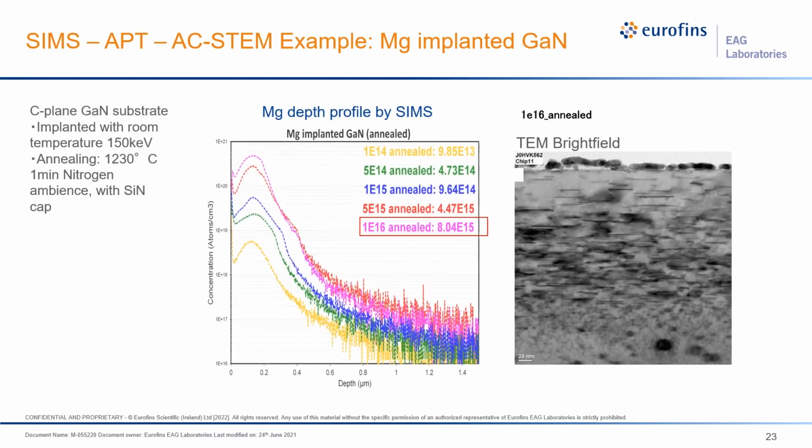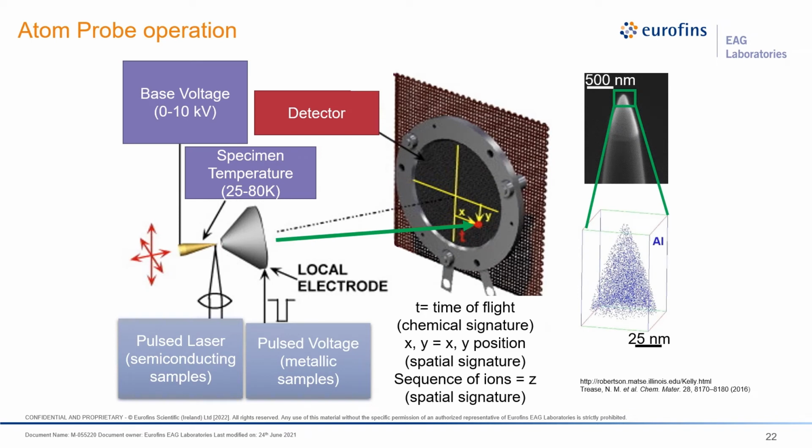This is very useful in the sense that we now have this three-dimensional data set that has all the atoms that were present in the tip itself, and we also know what element they were by their time of flight, right? So we can mass separate and understand what element by how long it takes to travel through the spectrometer. Then we get position plus composition essentially.